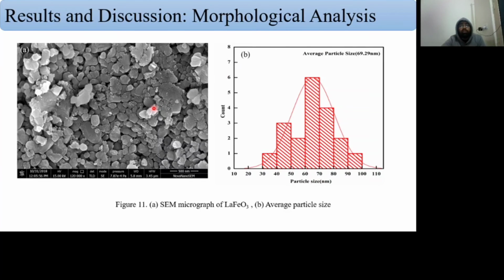Morphological analysis. In this image we can see the average particle size is around 69.29 nanometer. This average particle size was measured with the help of ImageJ software, and these large particles are nothing but agglomerated nanoparticles.